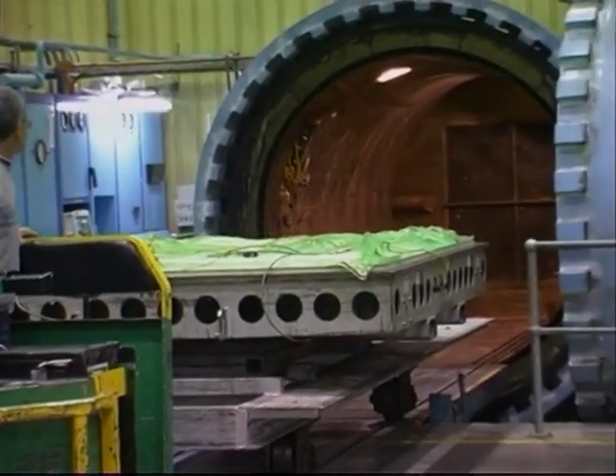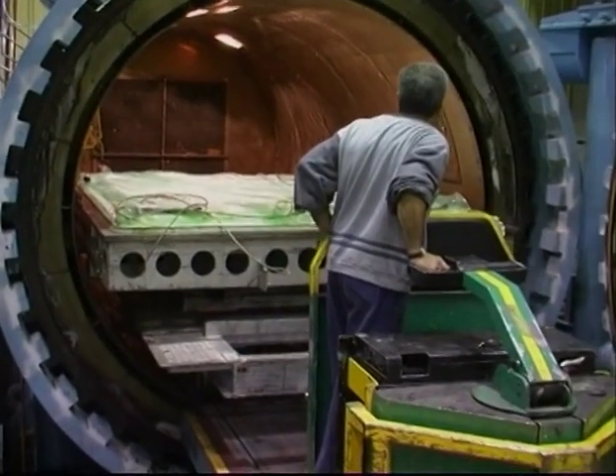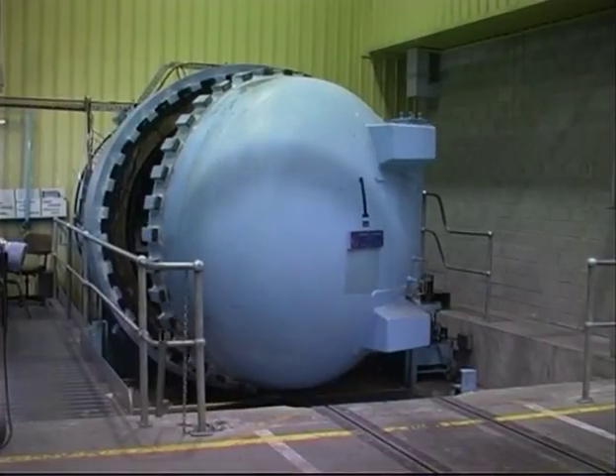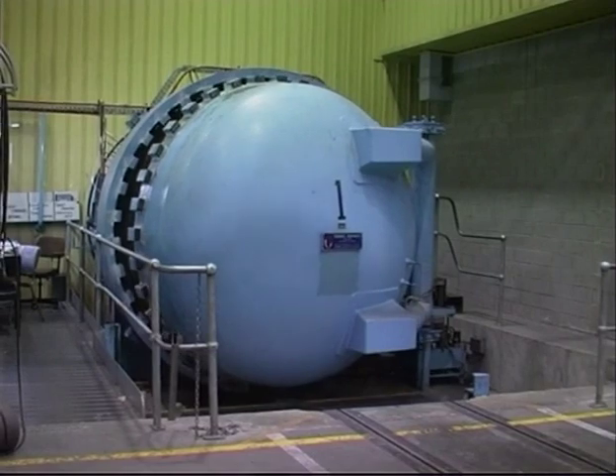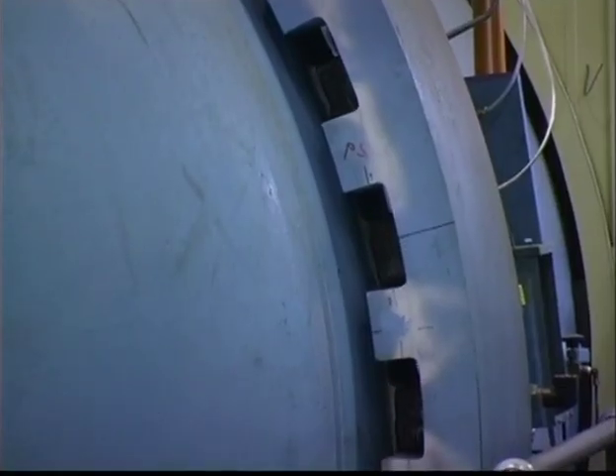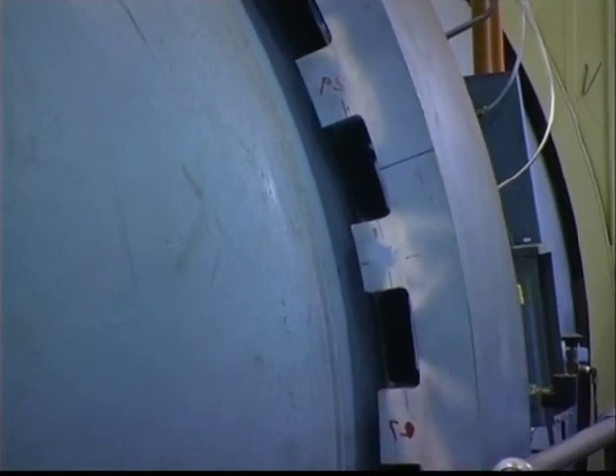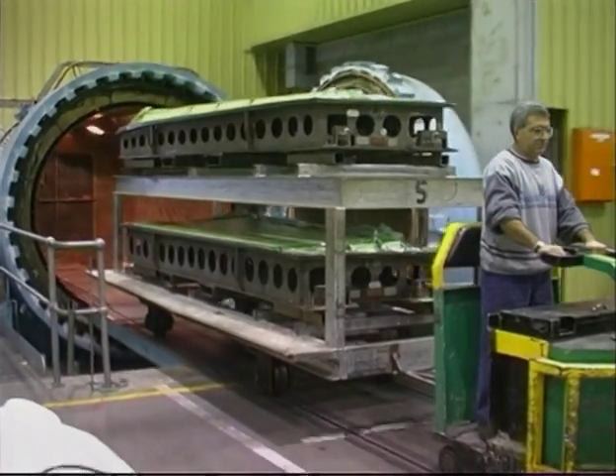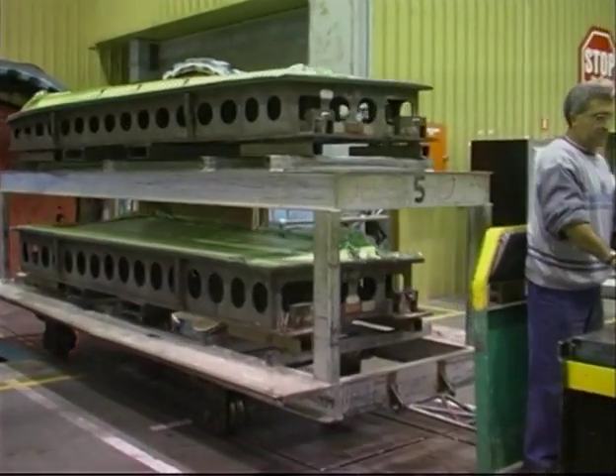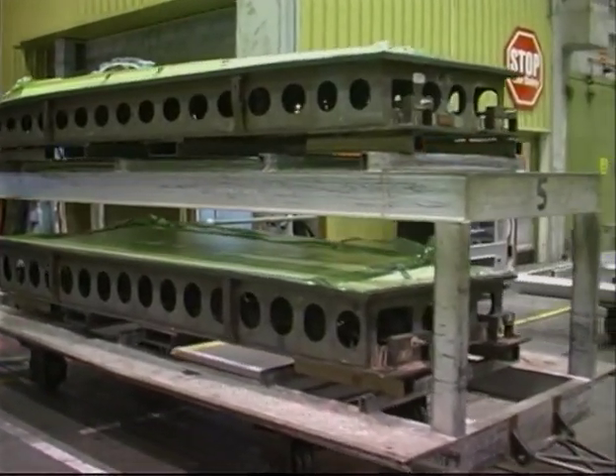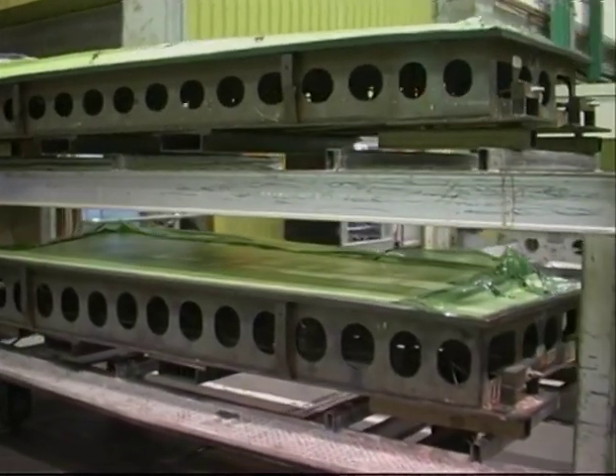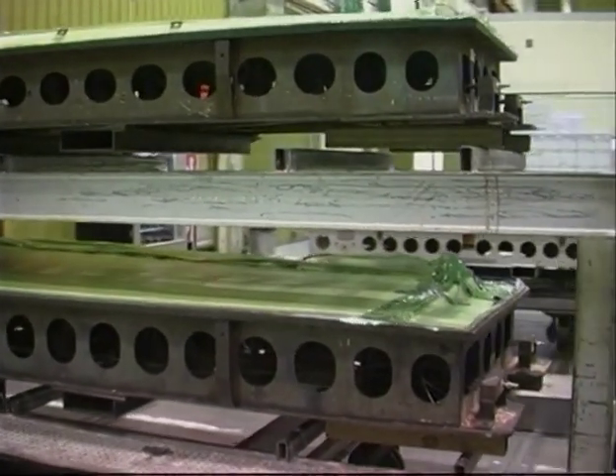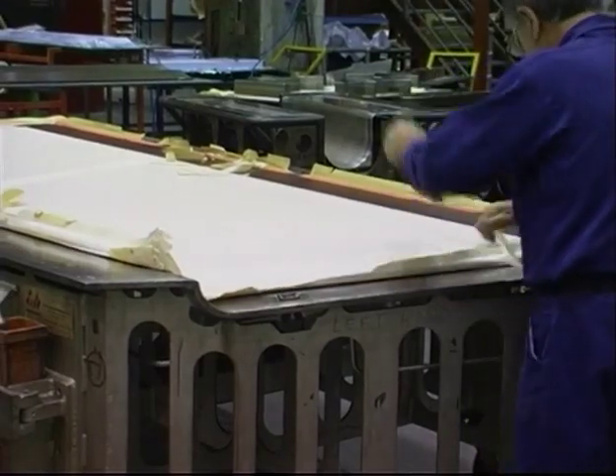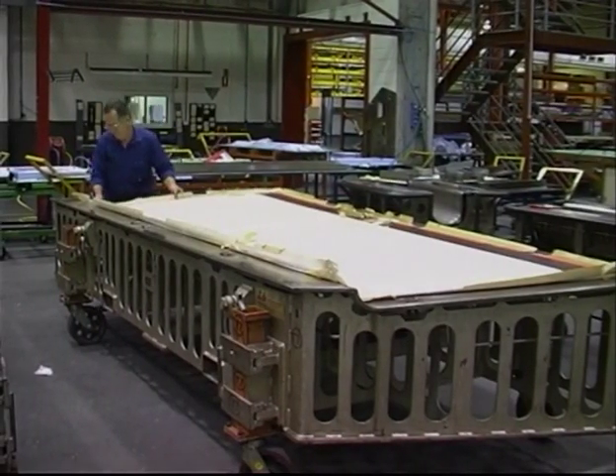The longest autoclave in the plant is 15 metres long and 4 metres in diameter. Thermocouples are also connected to closely monitor the temperature of the parts. The parts are heated to 180 degrees Celsius and held for 2 hours. The complete heating and cooling cycle takes approximately 6 hours. Some of the tools used cost up to $1 million each. They are very precise pieces of equipment. The tape is removed and the parts easily lifted off the tool.